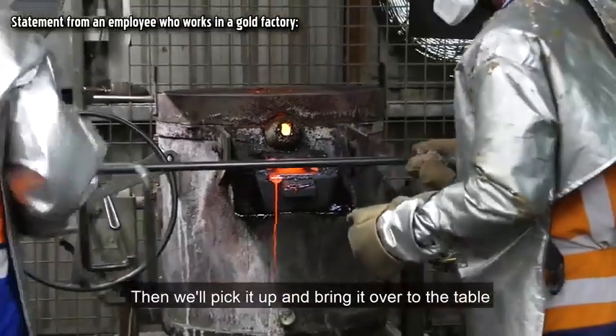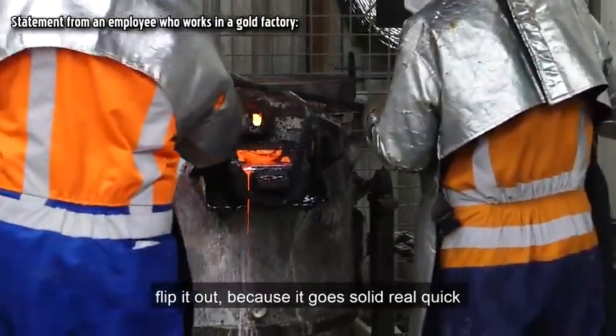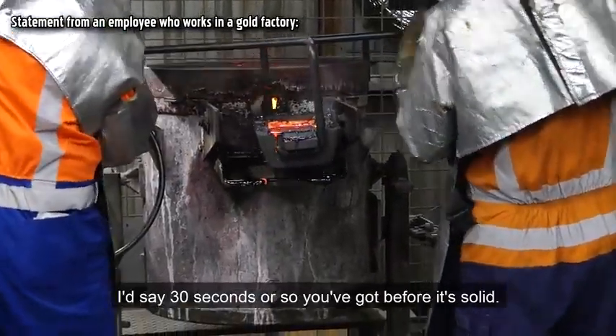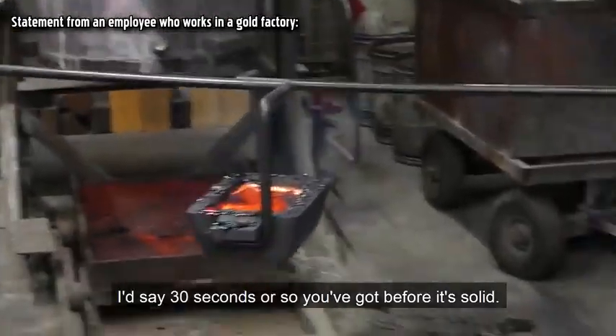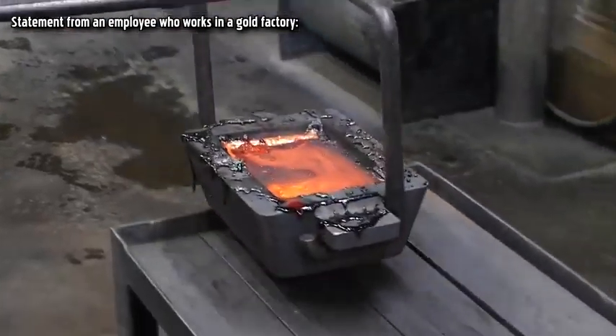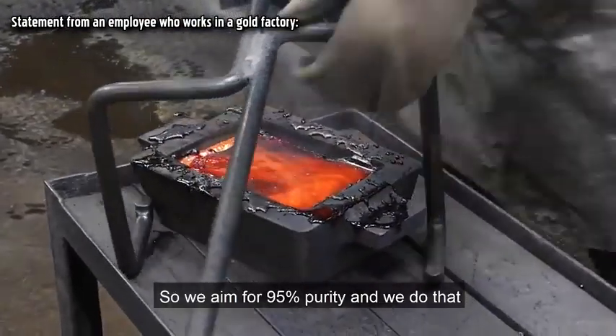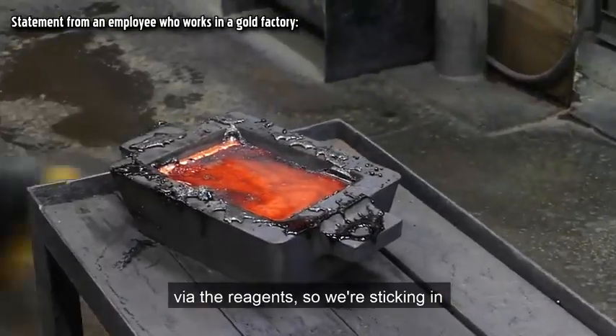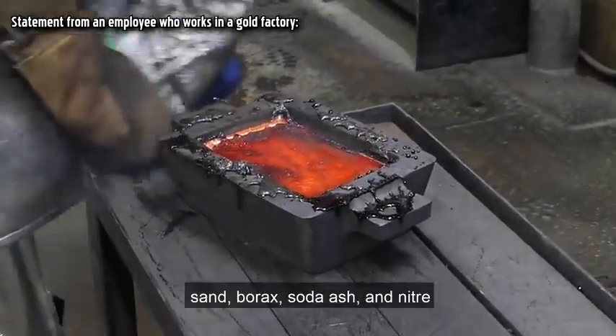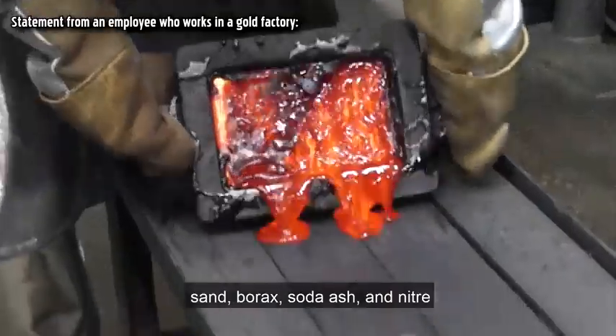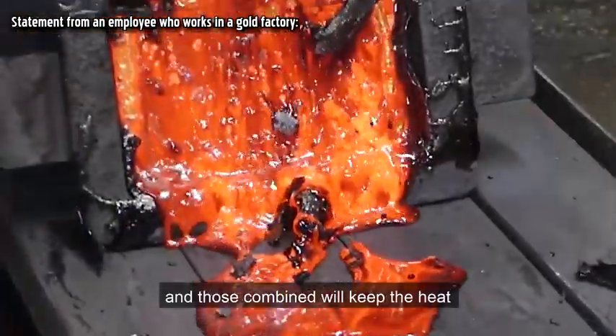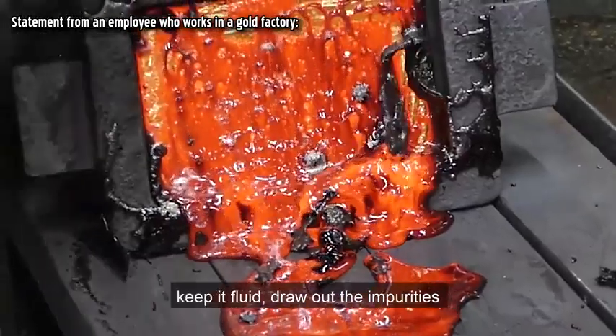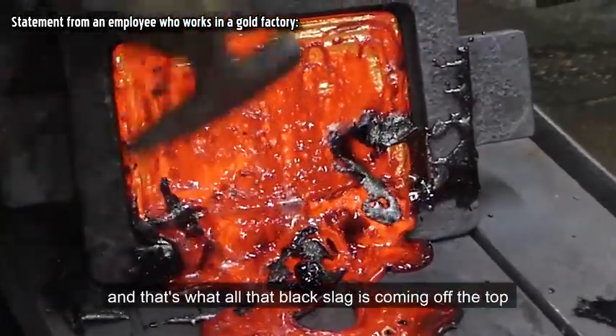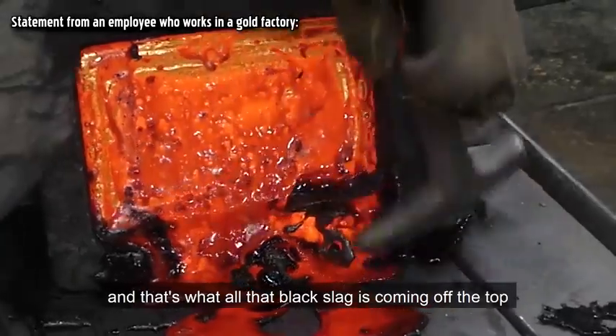Then we will pick it up and bring it over to the table, blip it out, because it goes solid real quick. I would say 30 seconds or so you have got before it is solid. So we aim for 95% purity, and we do that via the reagents. So we are sticking in sand, borax, soda ash, and niter, and those combined will keep the heat, keep it fluid, draw out the impurities, and that is what all the black slag is coming off the top, so it is not gold, it is black like obsidian.